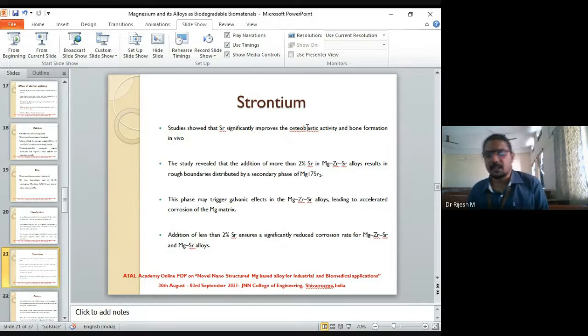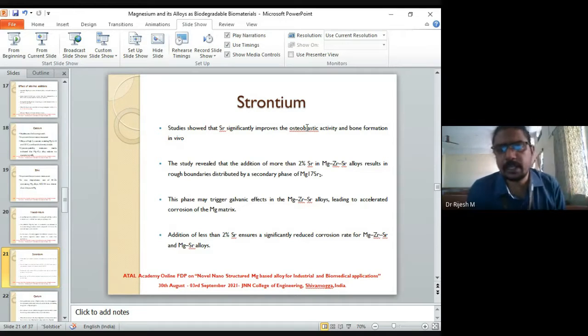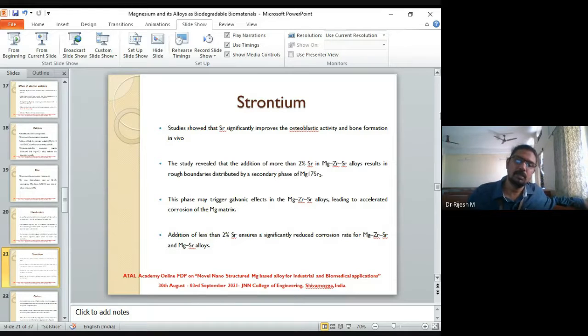Now, strontium is an excellent grain refiner. What I mean to say is that strontium will go and sit on the grain boundaries and form second phase particles. So magnesium, zinc, strontium alloys result in rough boundaries decorated by a secondary particle called Mg17Sr2.